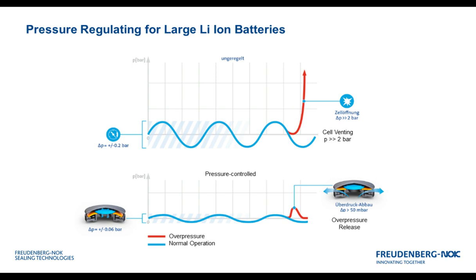And you can see here on the bottom, this is a pressure-controlled housing, where during the normal cycles of breathing and/or the normal temperature cycles of the day, you can see small pressure differences in the housing. And then in the event of a lithium-ion cell venting, you would see a small pressure increase, but not an overall pressure gain, preventing that damage to the housing.